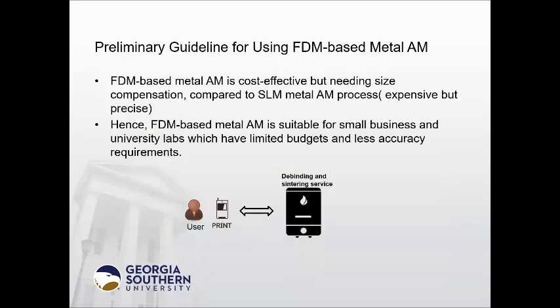Now here are some preliminary guidelines for using FDM-based metal additive manufacturing. So in comparison with SLM, the powder bed fusion-based additive manufacturing process for metal parts, FDM-based metal additive manufacturing is cheaper, and the disadvantage is that it needs size compensation due to the shrinkage after the debinding and the sintering process. The SLM part is expensive.